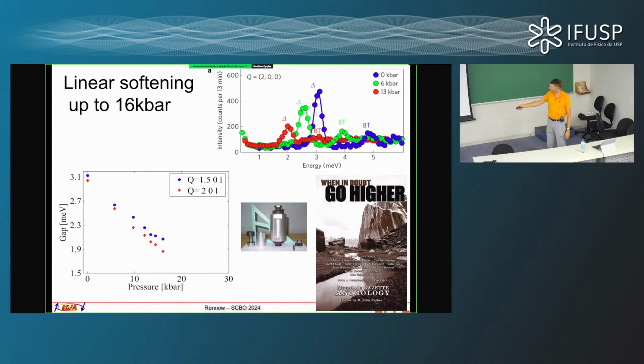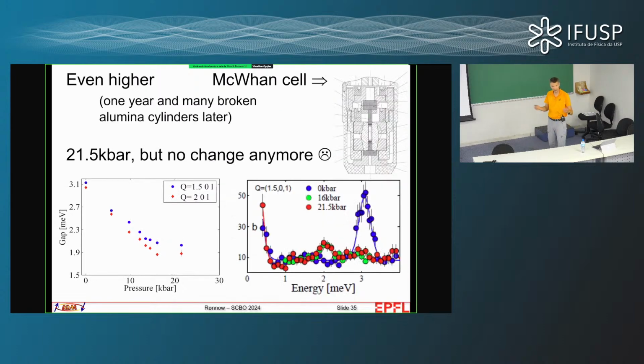It goes down. We managed to get it down to about 2 meV from 3, so we need another 2 to get it all the way down to the quantum phase transition. So that was done with one pressure cell. We found someone who had a bigger pressure cell. Now we need pressure cells that can have a big enough sample that we can do neutron scattering, get the neutrons in and out, etc.